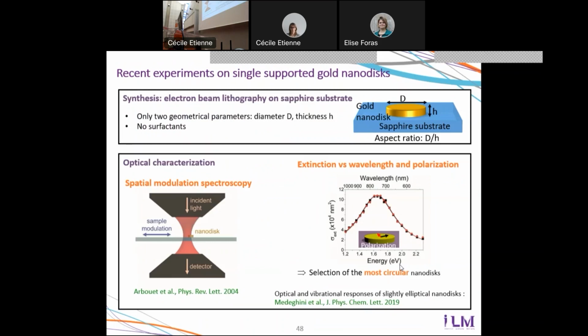So a nanodisc is an object that is characterized by two dimensions, diameter and thickness. And with electron beam lithography, it's possible to produce multiple nanodiscs with the same thickness, but with many different diameters, and therefore many different ratios between diameter and thickness, which will be the parameter of interest in the following.